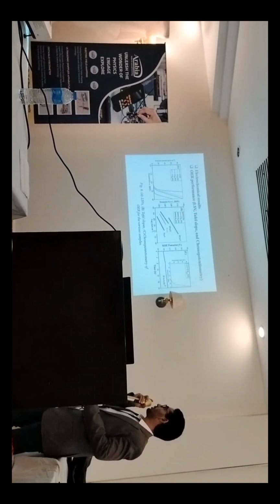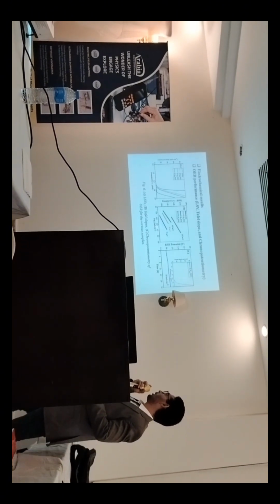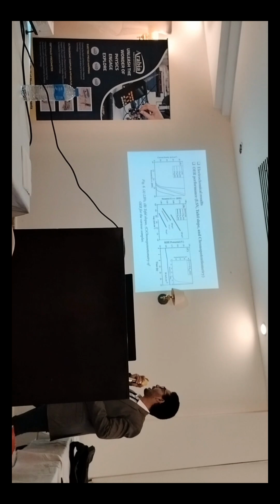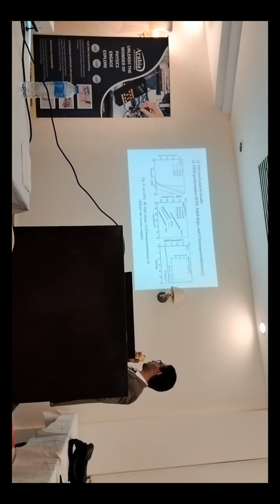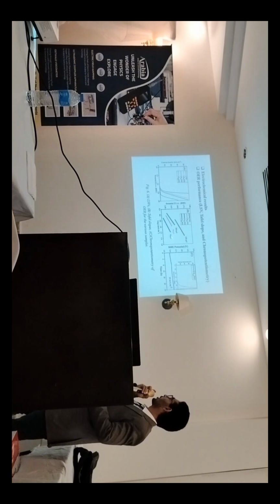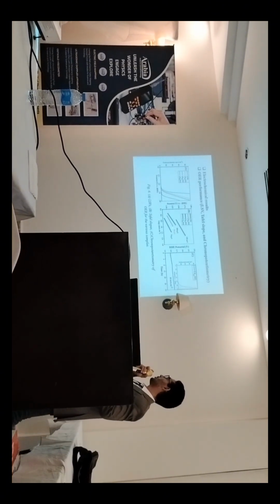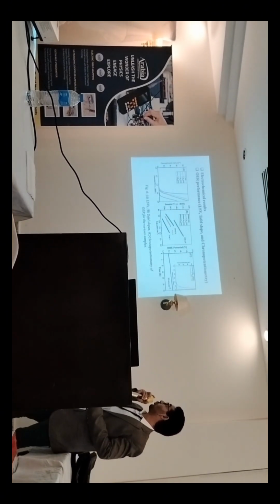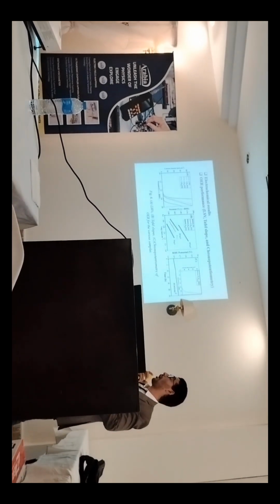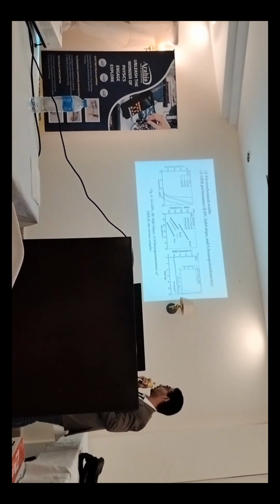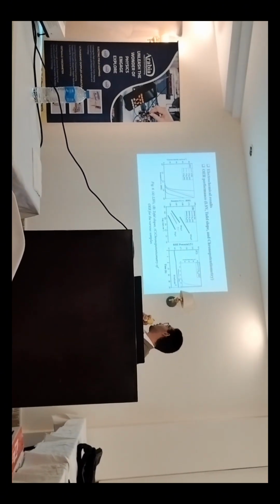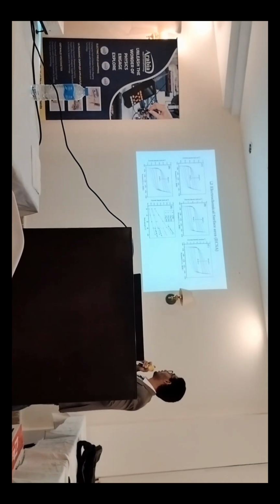And to check the mechanistic reactions, we have carried out kinetic analysis. We have carried out Tafel slope, and the lowest value, which means the best, was also related to 0.2 samarium doping. So we have carried out the chronopotentiometry, which is the IT curve, for 24 hours to produce 10 milliamperes per centimeter square as a current density.